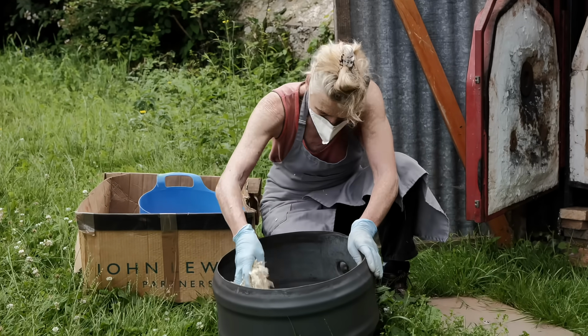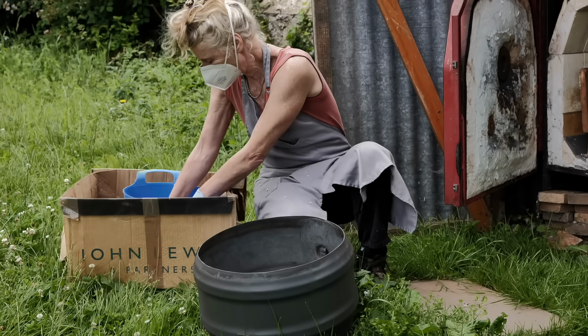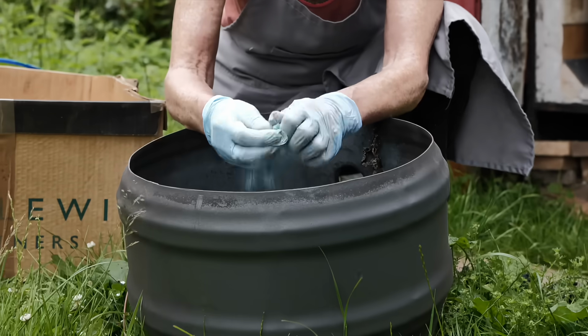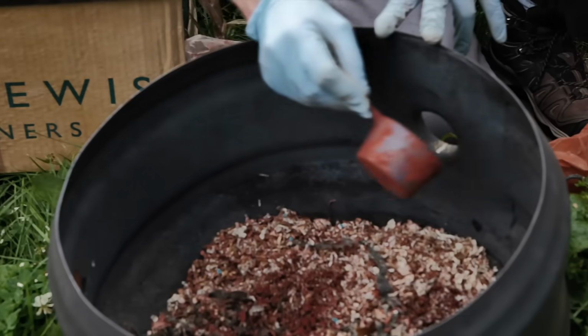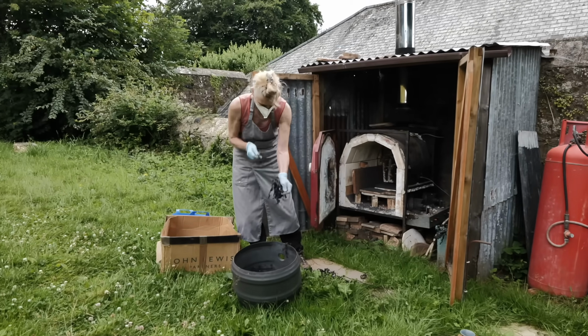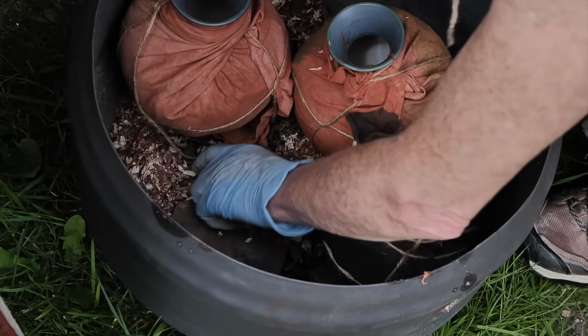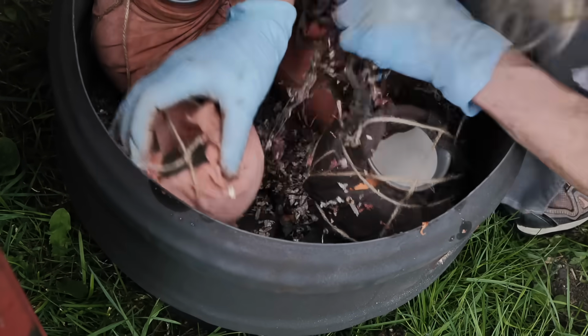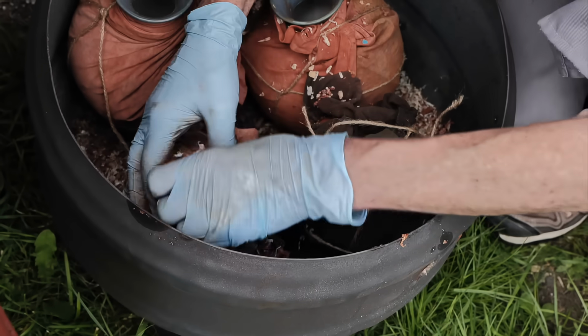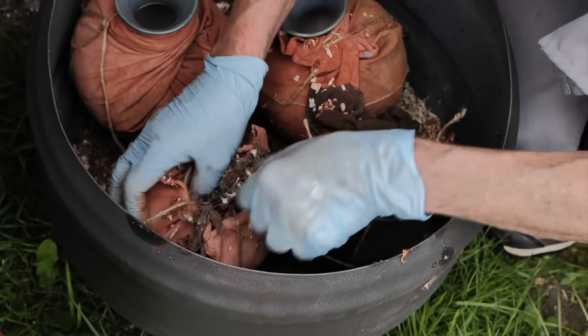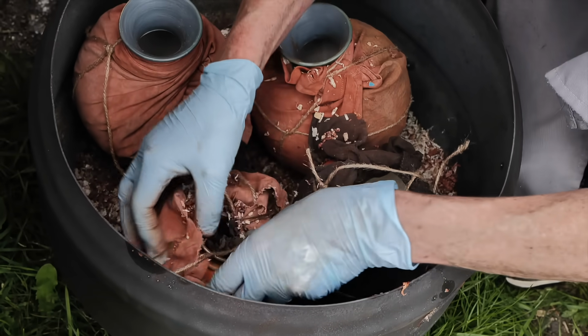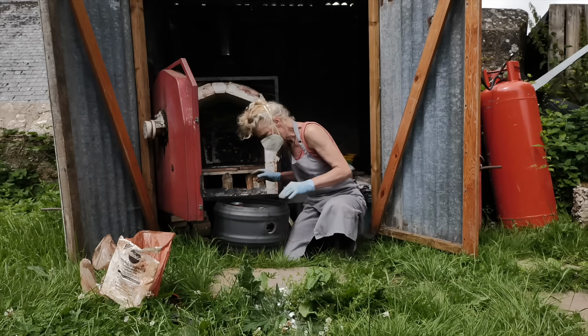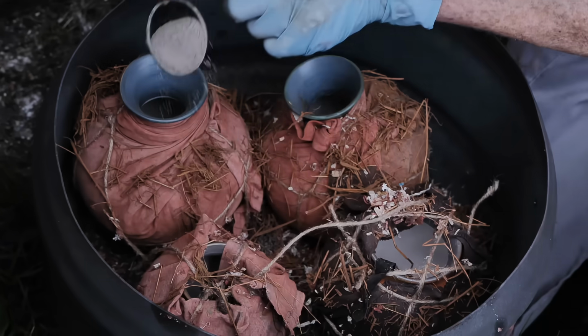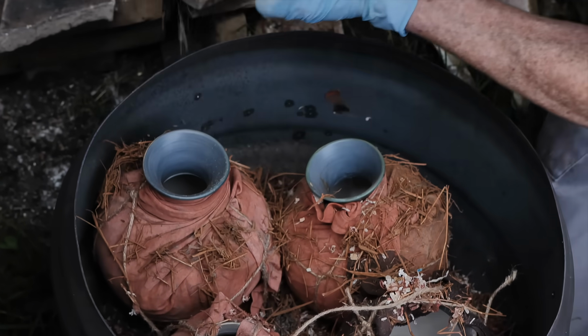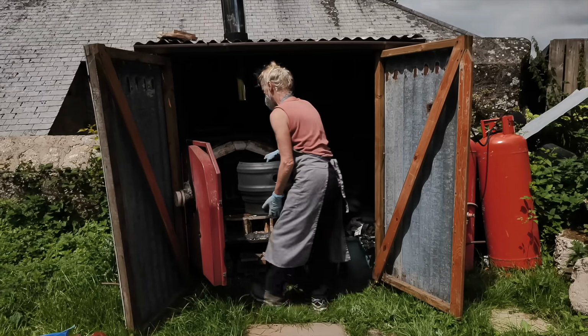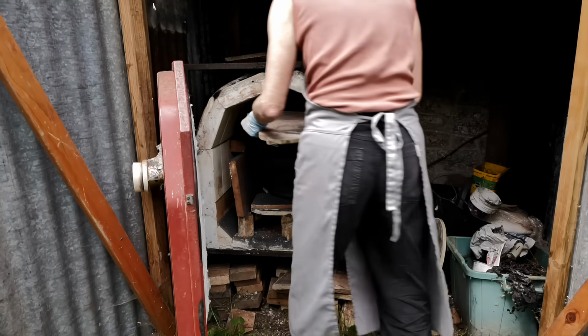So I place about 2.5 to 3 inches of wood shavings in the bottom of the pot. I add some oxides, copper sulfate, iron oxide, and pieces of dried seaweed will go in the mix. For this latest series of work, I do not want many smoke markings at the bottom where the piece would sit inside the sawdust. So I put them on little kiln bricks so they're raised up. I also have some hay, which I've coloured with a bit of iron oxide and copper carbonate, and sprinkle that around the top. I then place the saggar inside the gas kiln, put kiln shelves on top.